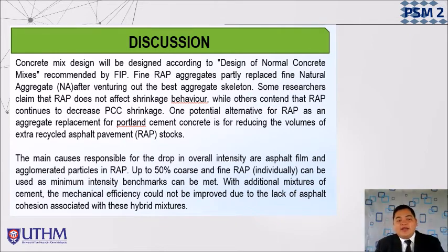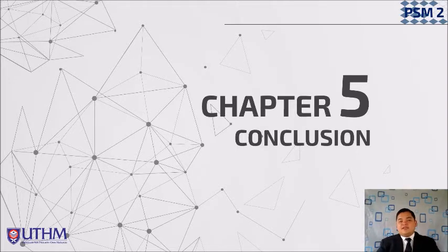Some researchers claim that RAP does not affect shrinkage behavior, while others contend that RAP continues to decrease PCC, Portland cement concrete shrinkage. One potential alternative for RAP as an aggregate replacement for Portland cement concrete is for reducing the volumes of extra RAP. The main cause responsible for the drop in overall strength is the asphalt film and agglomerate particles in RAP. As I mentioned earlier, the strength decrease in the concrete mix is caused by the other material called the asphalt film. Up to 50% coarse and fine RAP can be used as long as the minimum strength benchmark can be met. With additional mixture of cement, the mechanical efficiency could not be improved due to the lack of asphalt cohesion associated with this hybrid mixture.